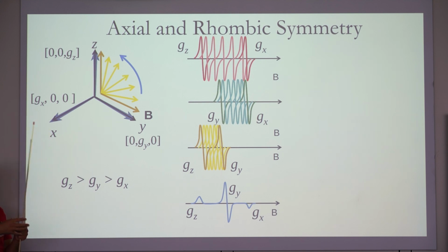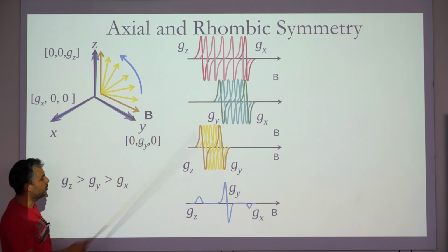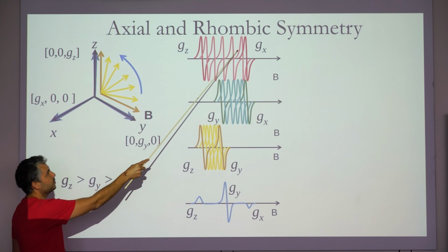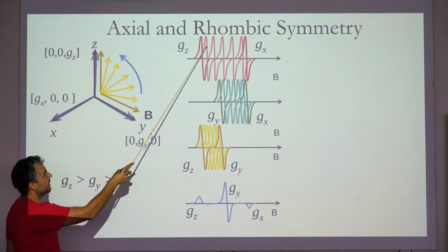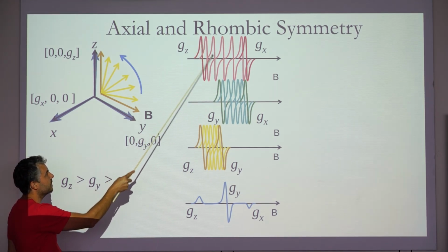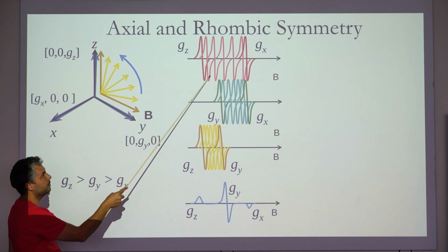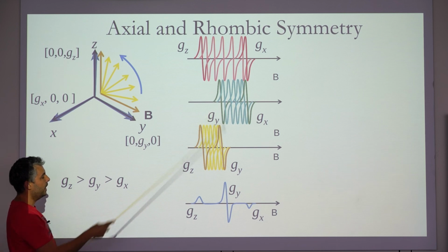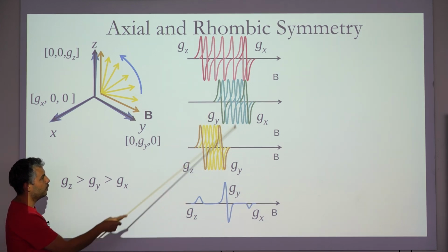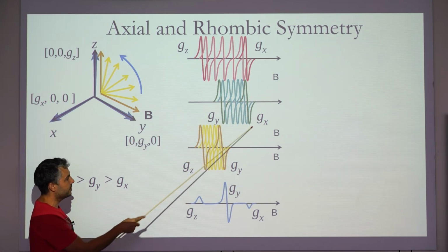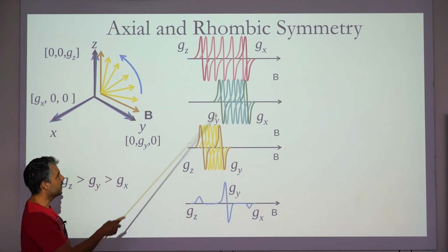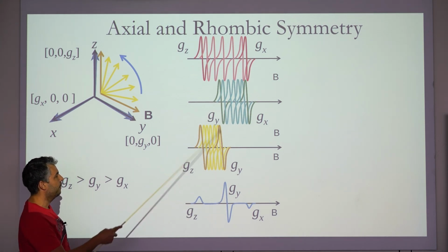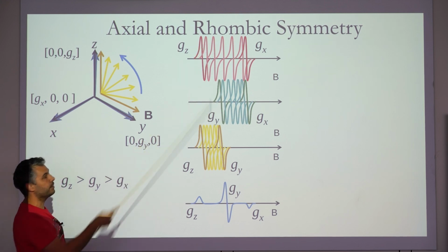The experiment is summing them up because you have molecules in all orientations. So if you can see that this value occurs here, all these values in between start to slightly cancel. The positive part of this resonance cancels with the negative part of the previous one. So you have 0 like here, and the same but opposite direction for the GX direction, and in between, because you have the GY value, it is repeated in several of the planes.